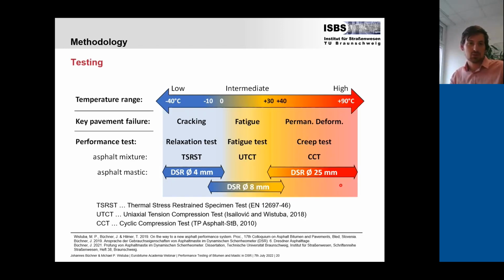Now, this is the testing methodology we were applying, separating the temperature range in low, intermediate, and high temperatures. And the key pavement failures here were low temperature cracking, intermediate temperature fatigue, and high temperature permanent deformation. Now we looked at performance tests: fatigue, creep, relaxation testing. For the asphalt mixture, we applied standardized and well-known tests where we had a lot of experience in our lab. So here we used the thermal stress restrained specimen test. We used the uniaxial tension compression test and the cyclic compression test here according to European standard, German standard, or some test here which was developed in our institute.